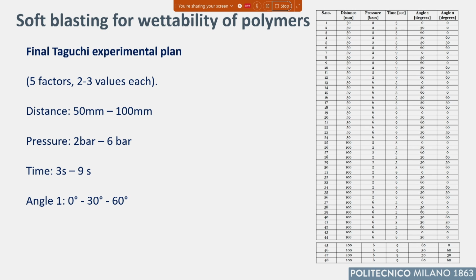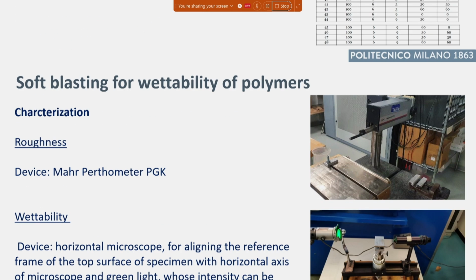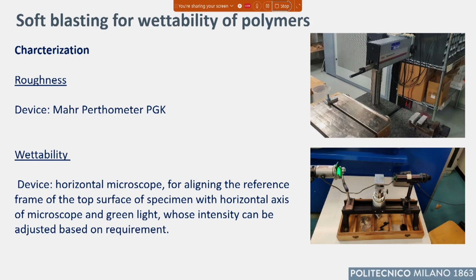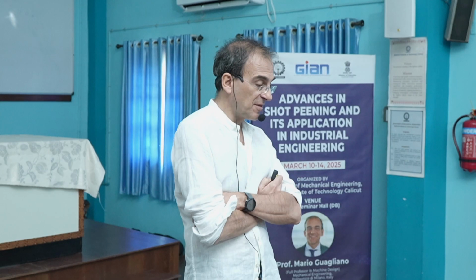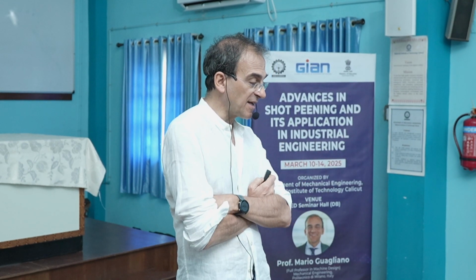We have 5 different factors. The distance was considered at 2 values, 50 millimeter or 100 millimeter. The pressure is 2 or 6 bar. The time is 3 or 9 seconds, and 3 different angles were considered: 0, 30 degree, and 60 degree. And here we have angle 1 and angle 2 that define the other direction of the tool where the sample is constrained. The roughness was measured by means of this profilometer, and the wettability was measured by using an optical microscope, tuned in such a way to obtain an accurate value of the angle of the drop, let's say.